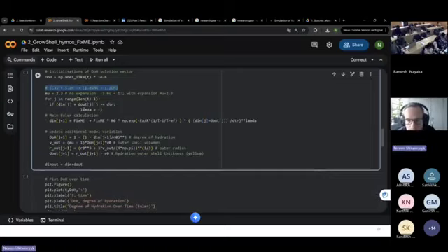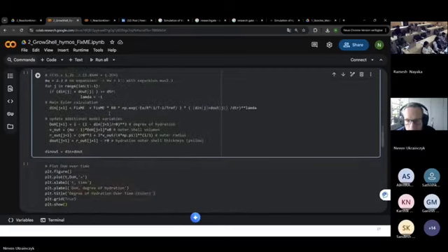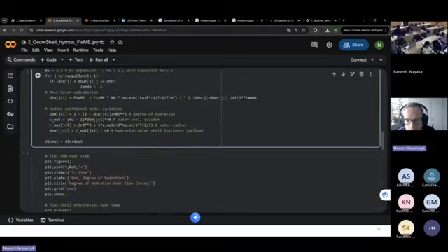And then we enter the loop, the Euler calculation loop. And this is just, if the threshold thickness is reached, and the shell thickness, the outer shell plus the inner shell, is bigger than the threshold thickness, which is half a micrometer here, then we switch the lambda parameter from 0 to -1. And then this factor becomes important.